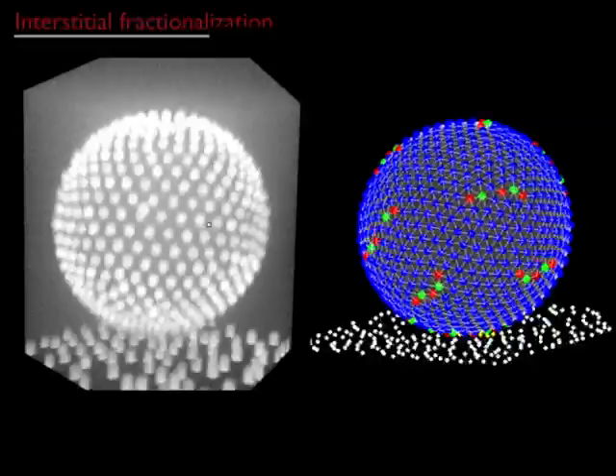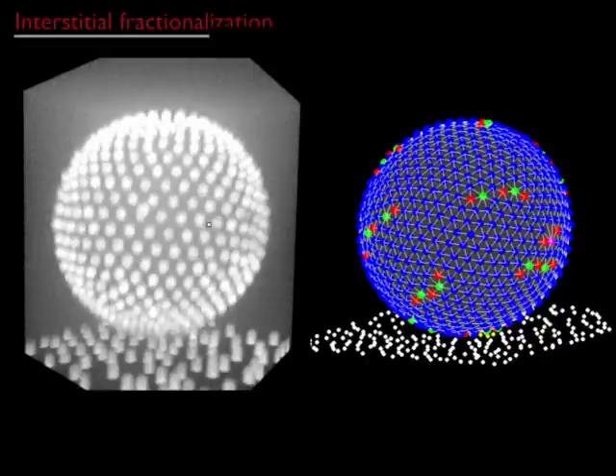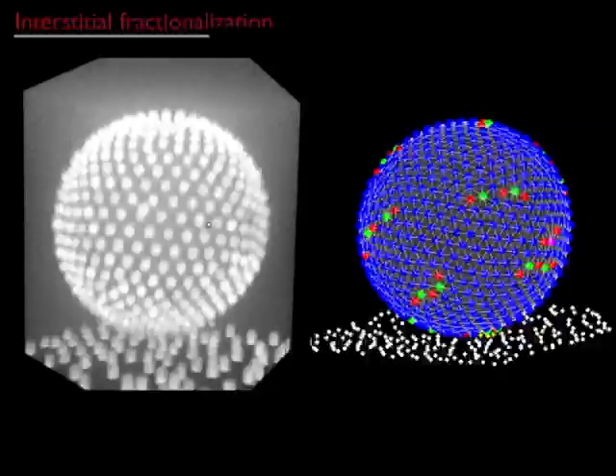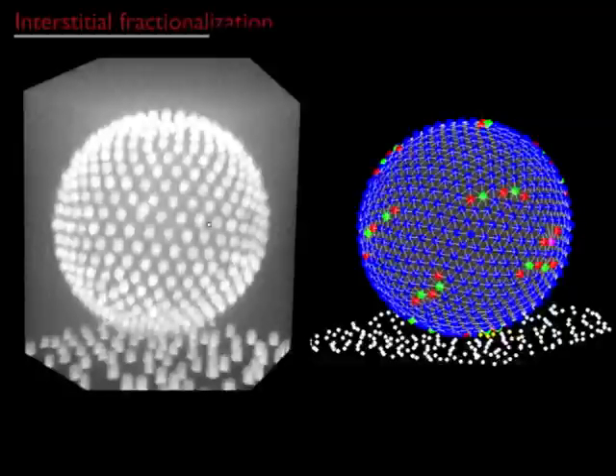It simply has to do with the fact that this region has the same density it had before. It's just a nice hexagonal lattice. But the density over here and over here, in these scars, in the disclinations and the scars, is different than it was before. That's where the density of the particle has gone. So we've really fractionalized the particle in this case, in the conventional way that you do in quantum mechanics when you write down solitons or density waves or whatever.